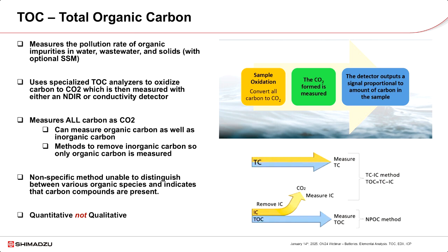There are specialized analyzers that have been developed to measure TOC, and basically these analyzers oxidize carbon in the samples to CO2, which is then measured by either an NDIR, a non-dispersive infrared detector, or a conductivity detector. These analyzers also have built-in mechanisms to speciate out organic carbon and inorganic carbon, making it possible to measure and report only the organic carbon present in the samples. It is important to understand that TOC measurement is quantitative, not qualitative, meaning that it can only determine the amount of carbon in a sample, but cannot determine what type of carbon it is or where it came from.